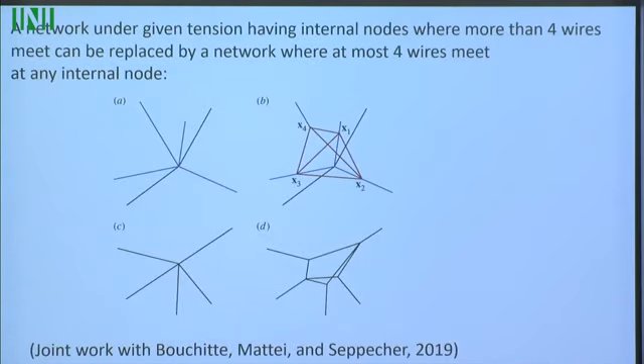In actual fact, this key feature of pentamodes is that they are uniloadable, and practically any elastic web under tension can be replaced by a uniloadable structure. If you take something like a bicycle, you've got all the spokes around the rim, and if one gets loose, you have to tighten it. If several get loose, you've got to tighten them one at a time. Wouldn't it be beautiful if you could have webs where you just tighten one of those cables, and the tension in the whole structure was exactly as you wanted it? And in fact, you can do that.